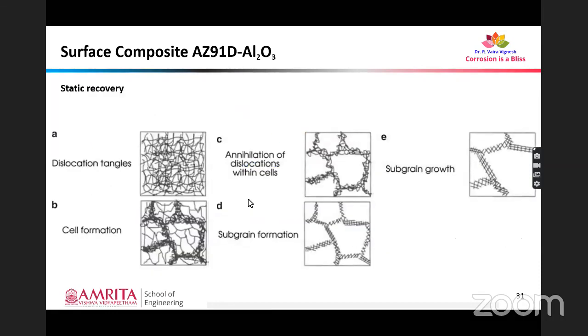And here's the process that happens when we have a static recovery. When the material is subjected to strain, there will be formation of dislocations. These dislocations, if they are present in a continuous manner, are called dislocation tangles, as we could literally observe from the image over here. Then if it is subjected to high temperature, there will be formation of cells and annihilation of dislocations within the cells, which will lead to formation of subgrains. And if the temperature is given for an extended period of time, the subgrains will be subjected to growth also.